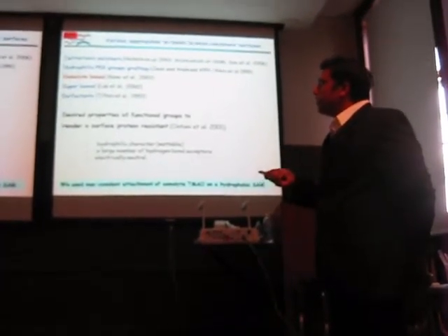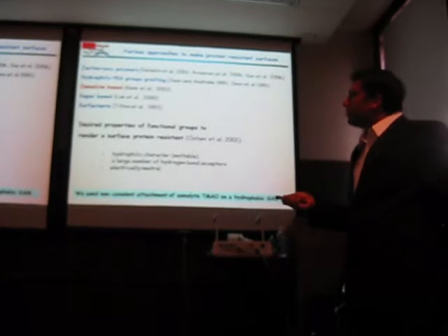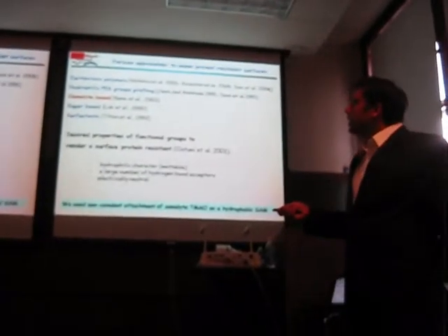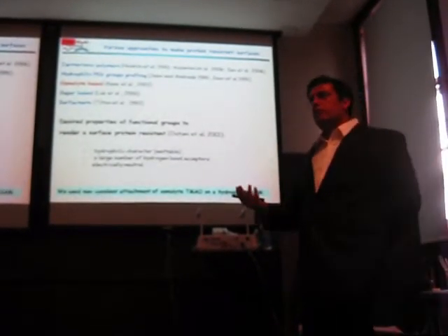We have used zwitterionic polymers, PEG, and there were studies by Professor Belfort in the past using betaine, and Professor Kane, sugar-based molecules and surfactants. These are the common rules of thumb which have been pointed out by Ostuni and Whitesides' group: typically, surfaces which are hydrophilic in nature, which are neutral, and which have hydrogen bond acceptors, meaning water is stable on the surface, tend to shield proteins from the surface. So these are the common rules of thumb.